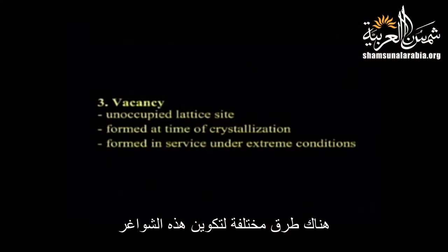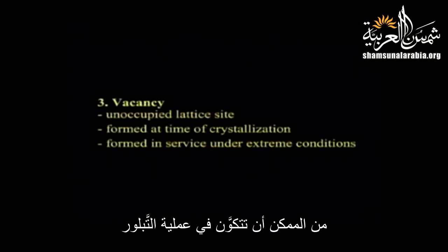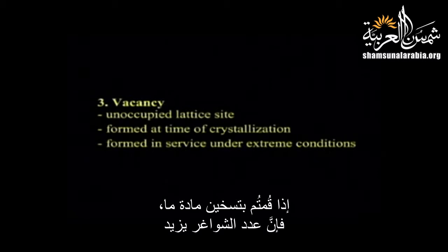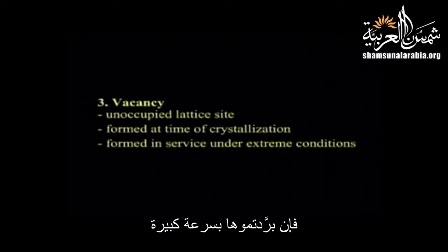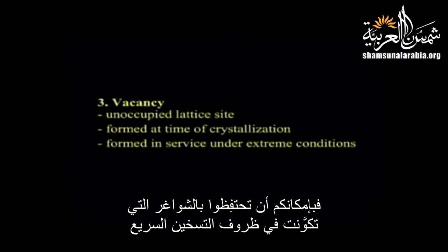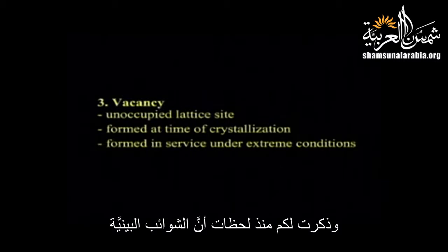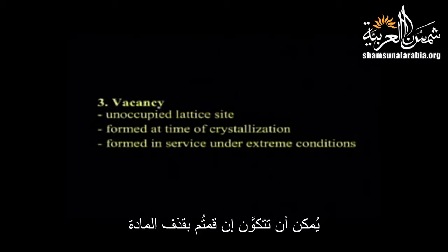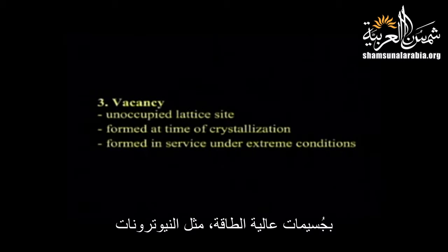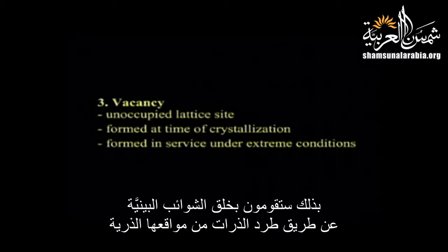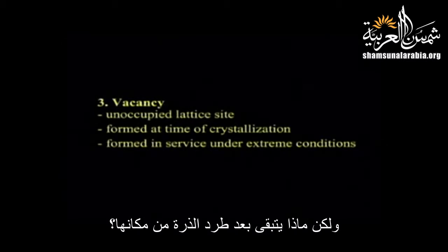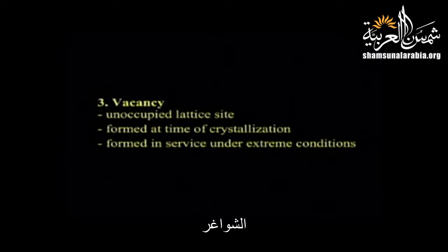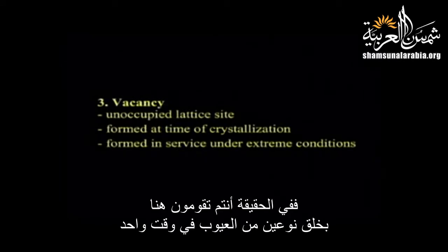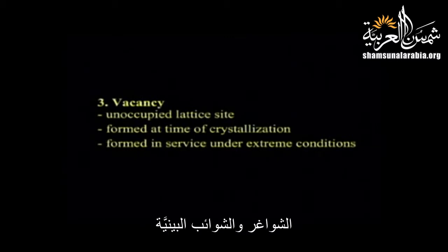And there are different ways to form these vacancies. They can be formed during crystallization. If you heat up a material, the number of vacancies increases. So if you quench it really quickly, you can actually trap the vacancies before they can leave. In service under extreme conditions, I mentioned just a moment ago that interstitials can be created if you irradiate a material. If you bombard it with energetic particles like neutrons, for instance, you'll create interstitials, sure, by knocking atoms out of their atomic sites. But what's left behind after you knock that atom out? Vacancies. So actually, you create two defects at the same time, vacancies and interstitials.